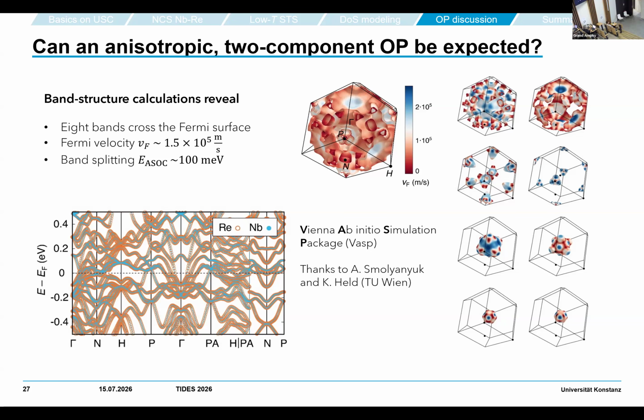And what we also learned from this analysis is that the Fermi velocity is in the order of 10 to the 5 meters per second, and the size of the spin, this anisotropic spin orbit coupling, is really large, in the range of 100 millielectronvolts. So we have strong spin orbit coupling.